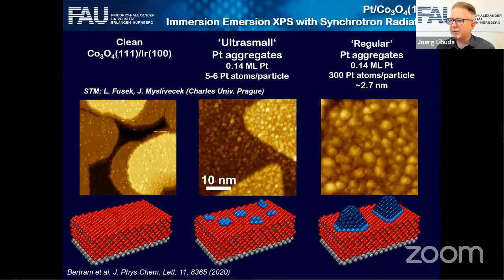In order to explore that, you can build model systems. I show an example here where we can look at the cobalt oxide film that I mentioned before. In some respects, it's similar to the cerium oxide film. We can make this cobalt oxide film and deposit small platinum nanoparticles on it, small aggregates or larger aggregates. The fascinating thing here is that by this surface science technique, you can control the size and make aggregates that are as small as just a few atoms, just 5-6 atoms in size on average. So extremely small aggregates, or if you like, you can also make bigger aggregates. These aggregates here have around 300 atoms, while those just have 5 or 6 atoms.